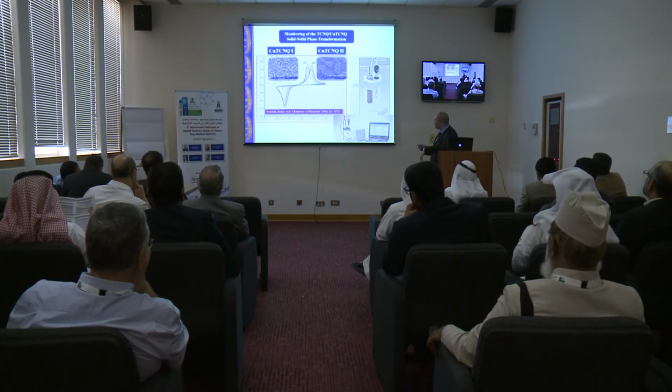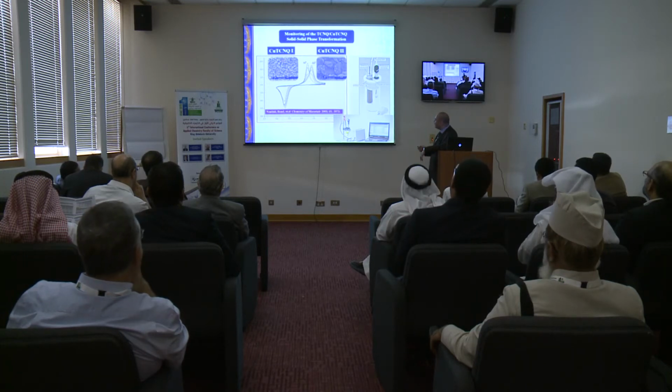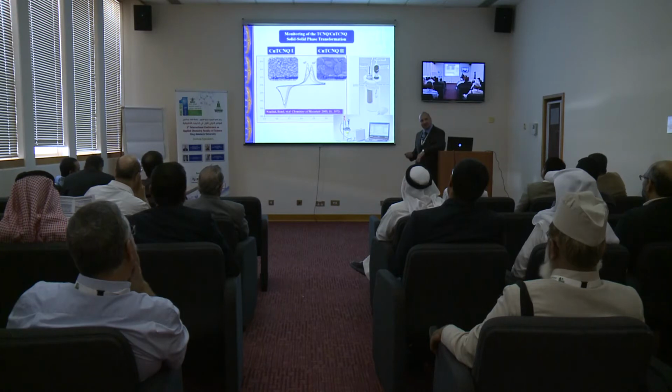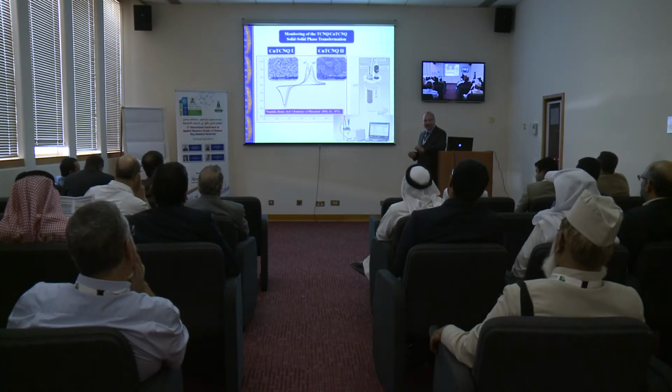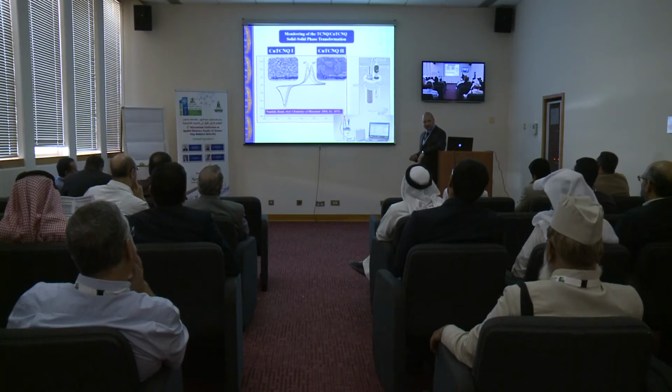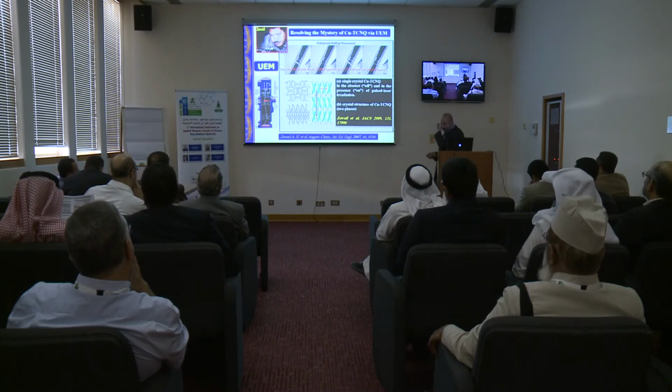When you oxidize back, what actually happens is you are oxidizing TCNQ minus to TCNQ, and then copper has to release to the solution. However, when you cycle this many times, you can see that this one is going down and this one is going up, which means, from the physical property of the material, that this copper TCNQ actually exists in two different phases, and they have two different morphologies. One of them is highly conducting and the other one is insulating. This is what we can gain from our electrochemistry background.